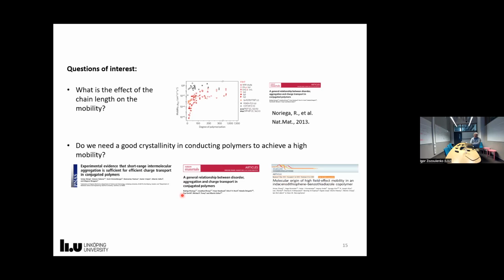Okay, so what questions did we address in our calculations? We wanted to understand the effect of chain length on mobility. There is a very interesting paper published almost 10 years ago, where people collected a lot of data from maybe tens of different studies relating the conductivity of polymers to the chain length of the polymer. Basically, they see that when the degree of polymerization increases, when the chain length increases, conductivity does not change much. So somehow you have this saturation.